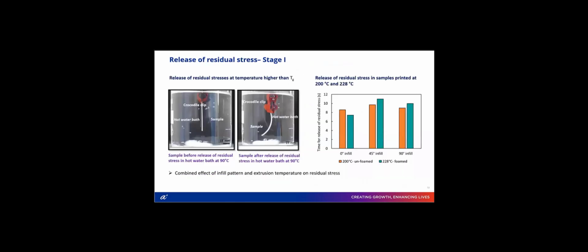The samples printed with different extrusion temperatures and different infill patterns undergo the stage 1 shape memory effect, the release of residual stress. The average residual stress release has been plotted here, where you can see the infill pattern and the extrusion temperature have a combined effect on the release of residual stress.